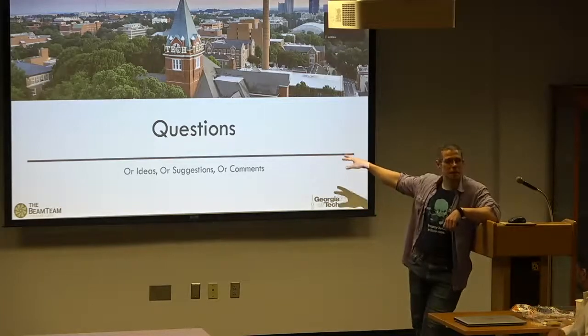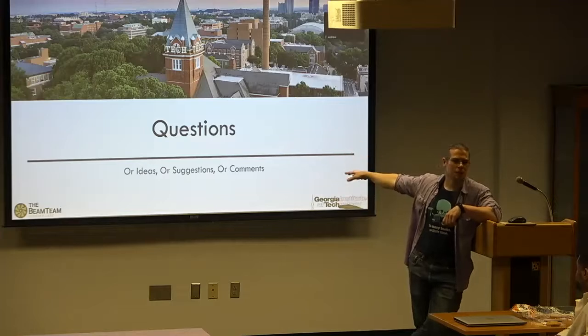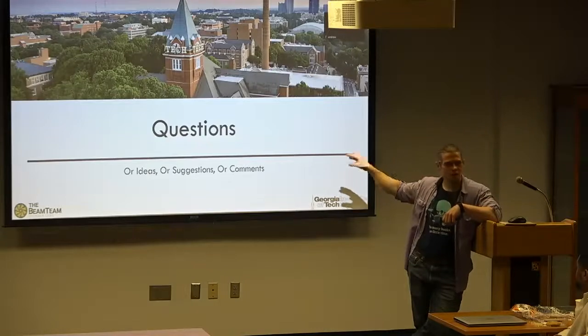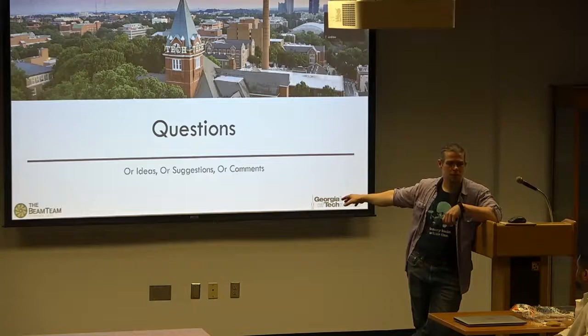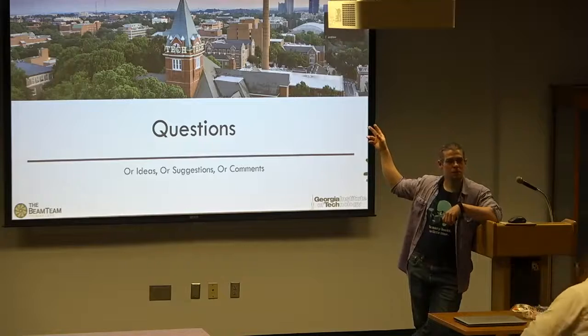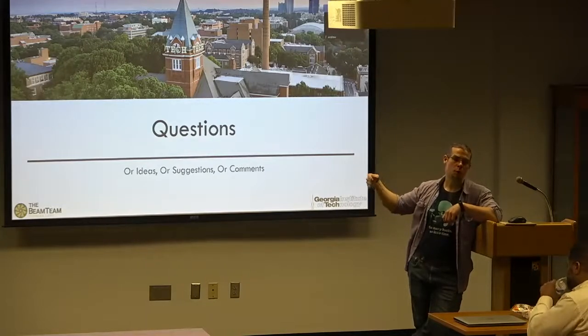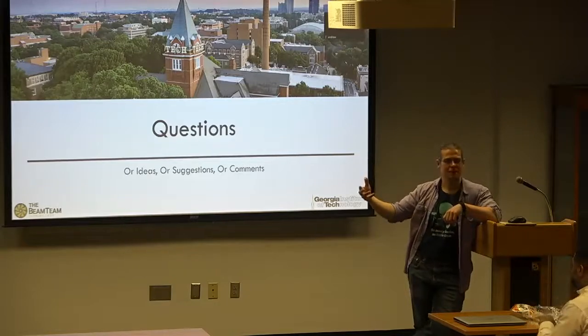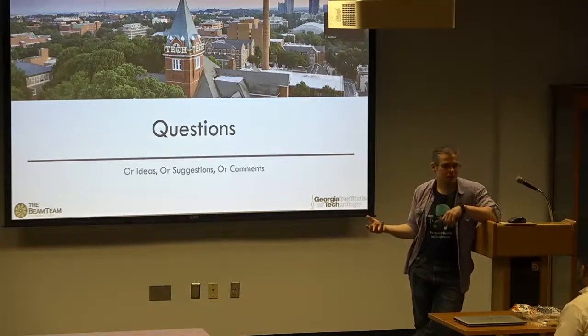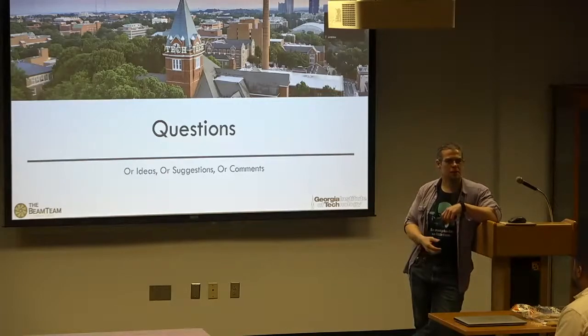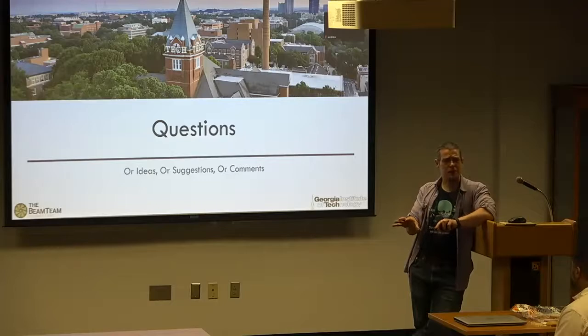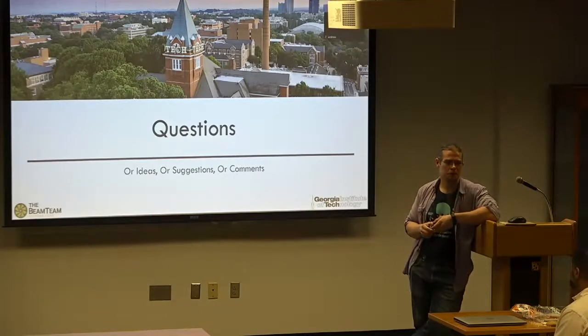The hope here is maybe not real-time feedback, but not interrupting the printing process too severely. If we can get a scan in under 2 minutes, then we're not dissipating all the heat that was built up in the part, we're not interrupting the process terribly, and we're able to collect data that we can use to train all of the other methods. The other methods could be used as feedback control: a pore formed here, so we should do this on the next pass to try and erase it. The problem is we don't have a lot of data for how to erase them either, which is why we want this layer by layer tomography without interrupting the physics of the printing process too much. Even if we can't use feedback control, it gives us data we can train all of the other systems off of to make them more reliable.